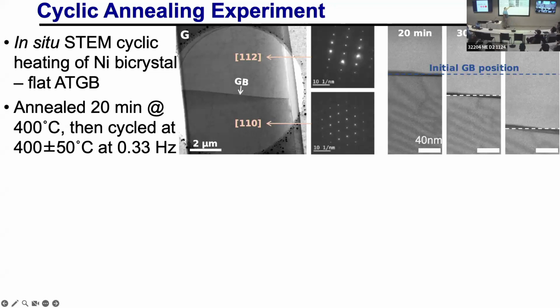And they put a heater on, and they heat and cool it. The temperature was 400 plus or minus 50 degrees. They did it at 0.33 hertz, and they did it for 20 minutes. And so you can see the difference in orientation of the two crystals. It's an electron diffraction pattern, and you can see it's not symmetric. And here's the position as a function of time. So after 20 minutes, it's there, and there, then there.